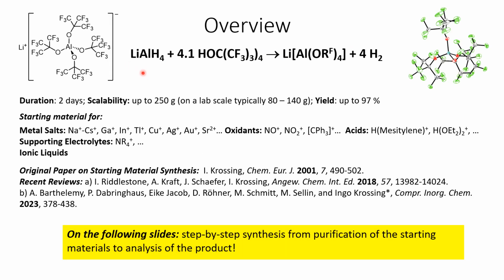The lithium salt can be simply prepared from commercially available starting materials, namely lithium aluminum hydride and perfluoro-tert-butanol. The reaction takes about 2 days and can be scaled up to about 250 grams. In our lab, we usually do reactions yielding 80 to 140 grams of the lithium salt. The reaction is quantitative and gives us the product in up to 97% yield.